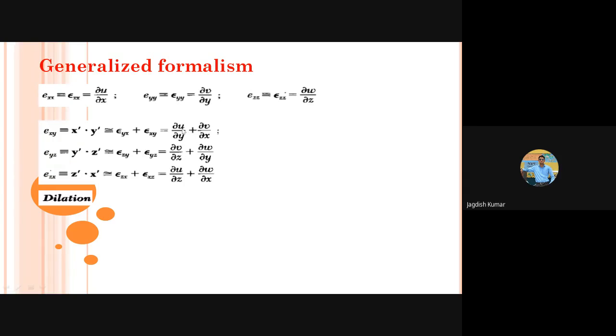Then in X-ray, you can find out those UVW parameters. And from those UVW parameters, you can find out further the different strain values, right? And once you know these different strain values, we can find out the vectors back, or once we have the data, we can do reverse calculations to get these x dash, y dash, z dash. And once we have them, we can find out what will be the change in volume. So then we can define physically measurable quantities.